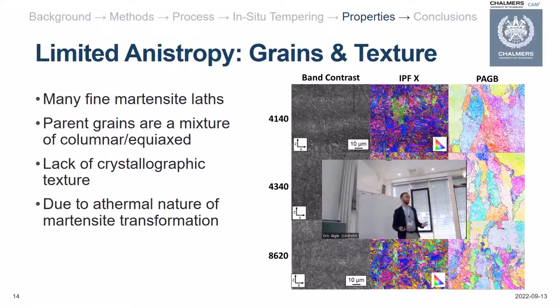They're going to grow athermally into a bunch of different variants that are more dependent upon the size of the parent grains or the composition of your alloy. And even if we look at the parent grains, so the kind of high angle grain boundaries, they also don't have necessarily just long columnar grains, they have a mixture of the two. So this is one of the major reasons why we're having that limitation.